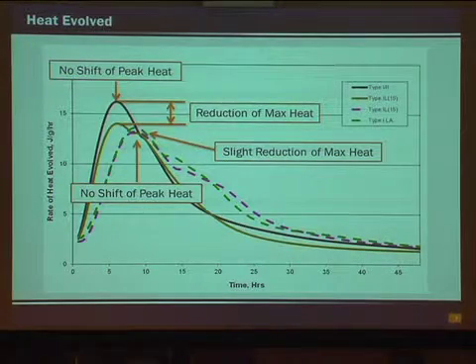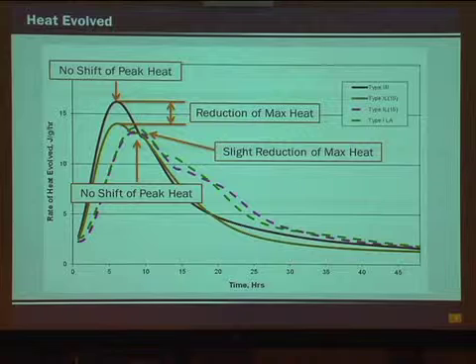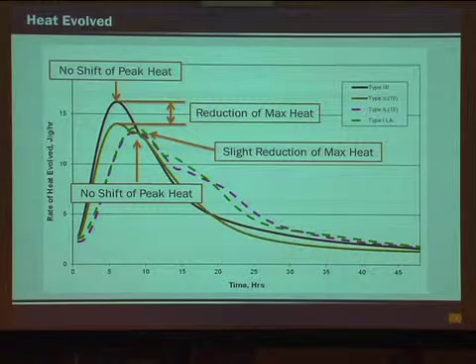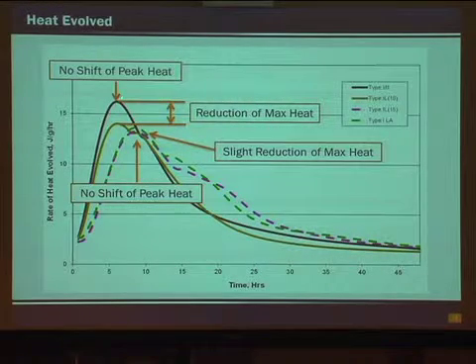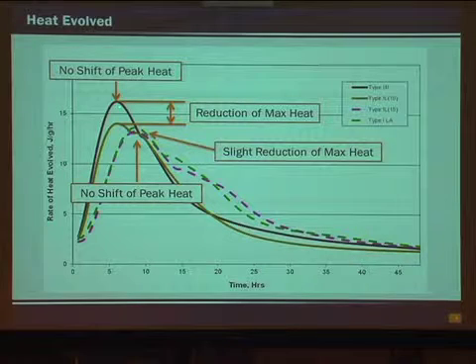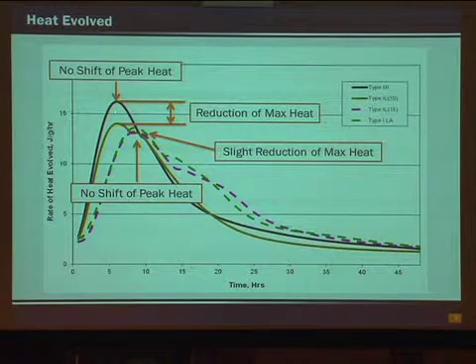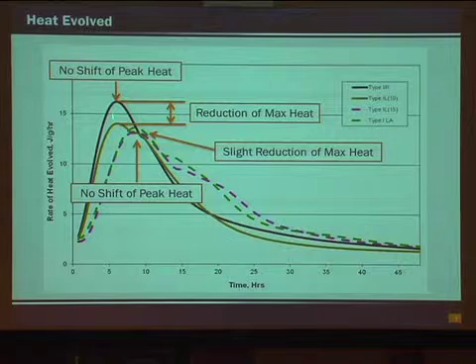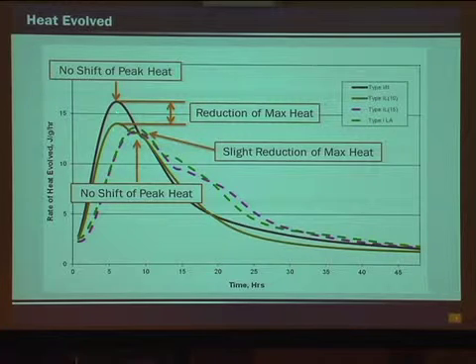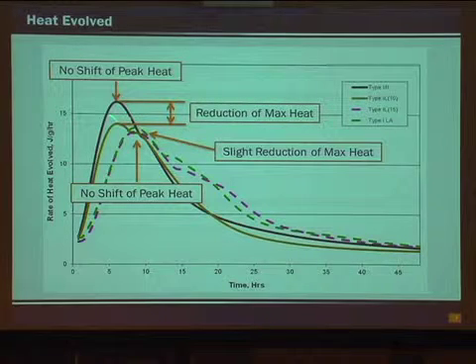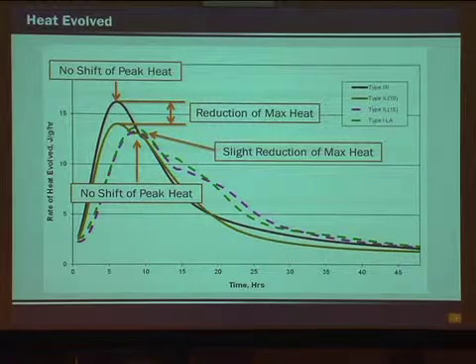This is just a heat plot of a couple different Portland limestone cements and their parent cement. You can see this particular one, even because we reduced 10% clinker, we do have a reduction in heat. You have less material in there producing heat, so you do have some reduction. However, there's no shift. A shift going left and right would indicate a difference in setting, and we have no shift there, so it doesn't hurt setting properties.